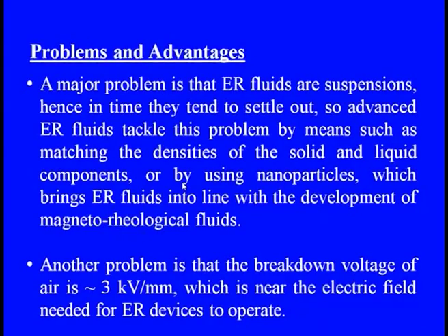Lastly, the major problem in ER fluids is the suspension. Hence, in time they tend to settle down. The advanced ER fluid tackles this problem by matching the densities of the solid and liquid components, or by using nanoparticles, which brings ER fluid into line with the development of magneto-rheological fluids. Another problem is the breakdown voltage of air, 3 kilovolts per millimeter, which is near the electric field needed for an ER device to operate.